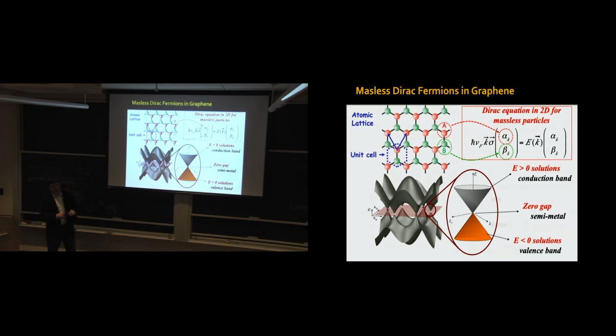Another thing to take into account is that there are several of these double Dirac cones in the graphene electronic structure. Only 2 of them are independent — the others are copies by reciprocal lattice vectors, but we have 2 of them, the K and the K-prime valleys. And then we also have spin. This means that electrons in graphene have a 4-fold degeneracy: spin up, spin down, valley K, valley K-prime. Just remember 4 for the rest of the talk — it will appear later.